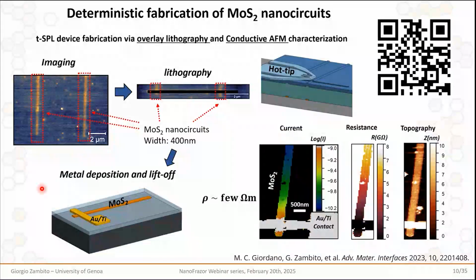And in this specific case, we exploited this very simple device configuration to conduct a conductive AFM characterization measurement, which allowed us to observe, along with topography, also resistance and current maps, which allowed us to extrapolate an estimate of the resistivity of our MoS2 nanofingers and nanocircuits, which lies in line with the other results dealing with CVD-grown TMDs.